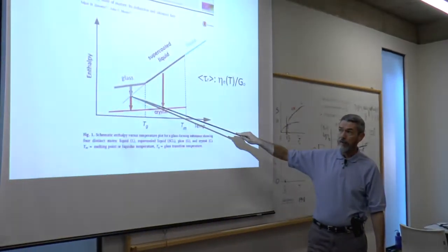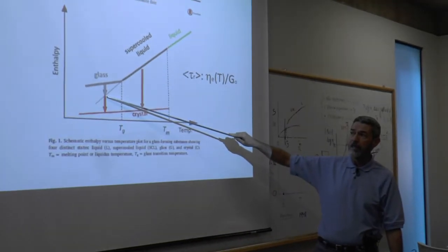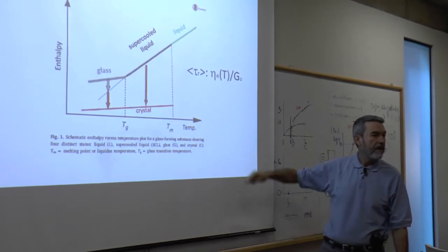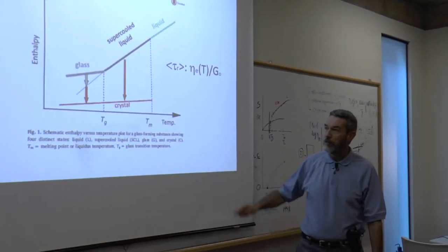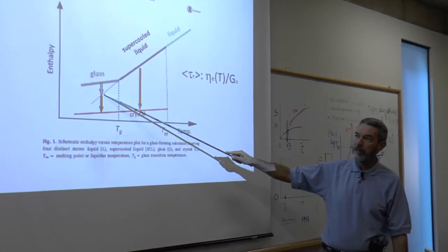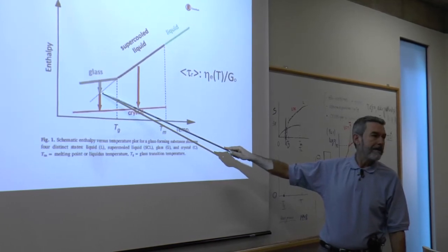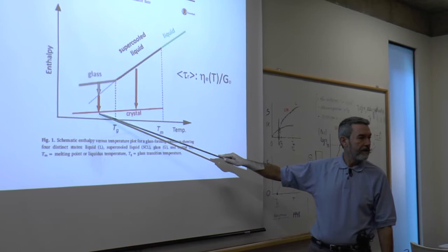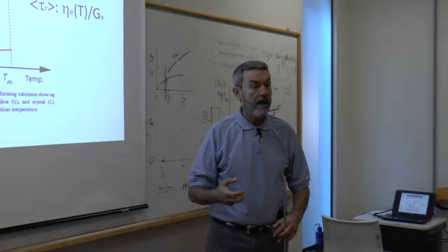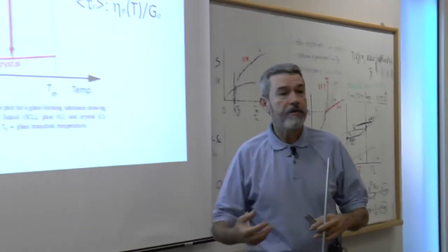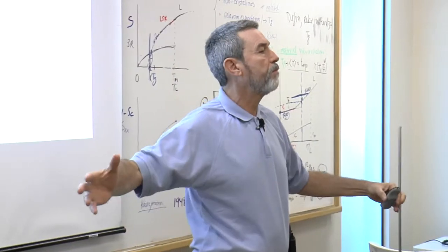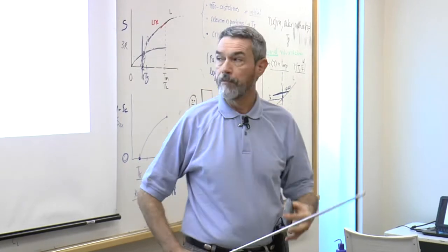And then, after it reaches the supercooled liquid state, it will continue its path towards the crystal phase and then will crystallize. So the glass is unstable against the supercooled liquid, and the supercooled liquid is metastable against the crystal. Then there is a thermodynamic barrier for nucleation of crystals. After nucleation starts, after the first critical nucleus is formed, crystal growth takes over spontaneously.